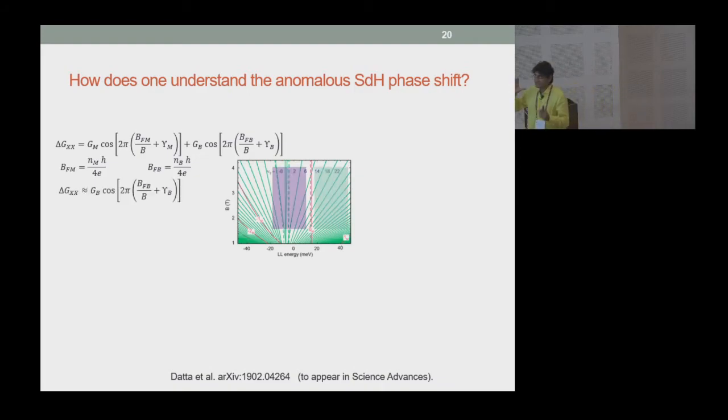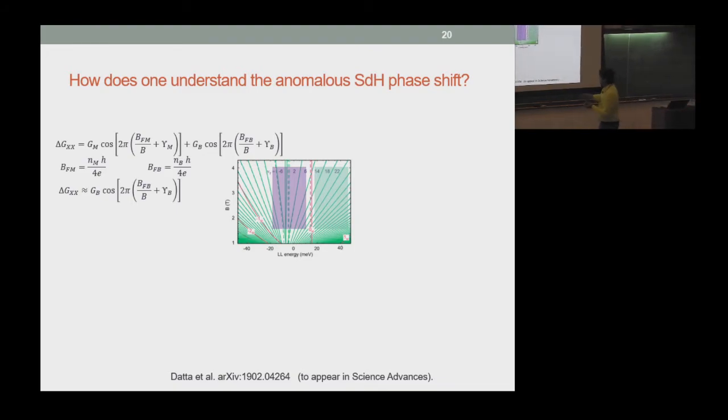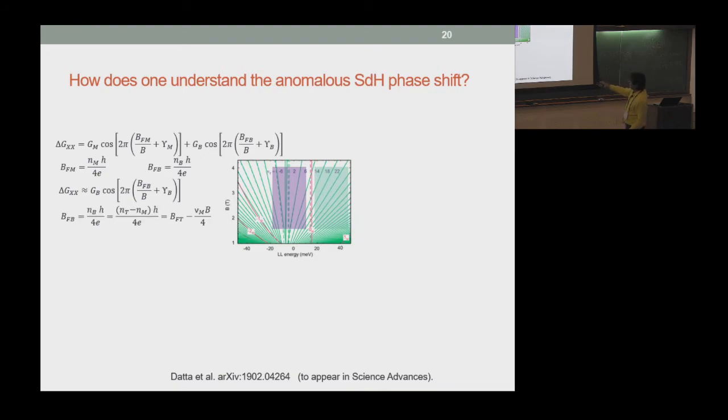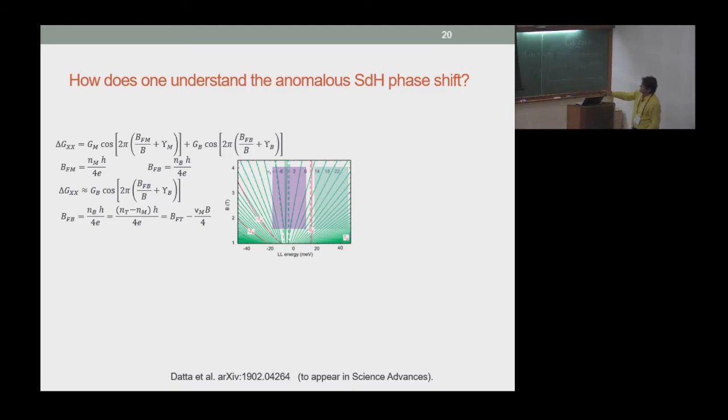Now, this is sort of the key part, and this is the parameter space in which we do analysis in the experiment. Here, precisely the Dirac band, which is the n equals 0 Landau level, is exactly fully filled if I'm looking here, or fully empty when I'm here, because this guy never disperses with magnetic field. This really remains stable. Now, what that results in is the fact that this occupancy doesn't change, but I need to reflect that in the occupation density inside the bilayer-like band, because monolayer remains almost constant.